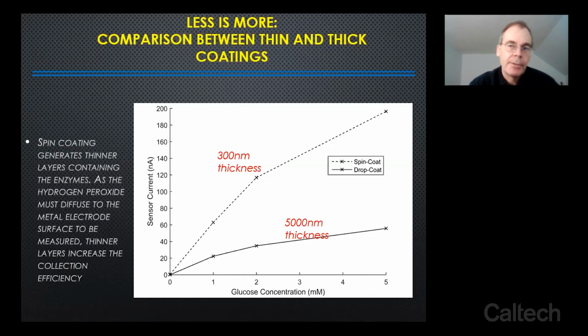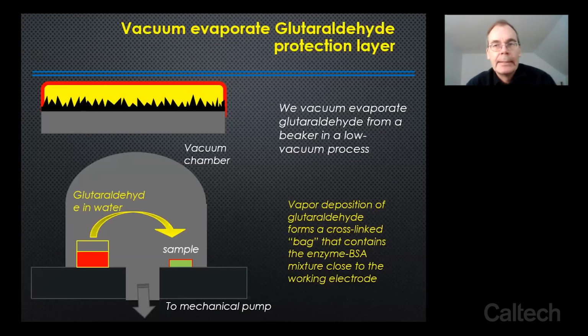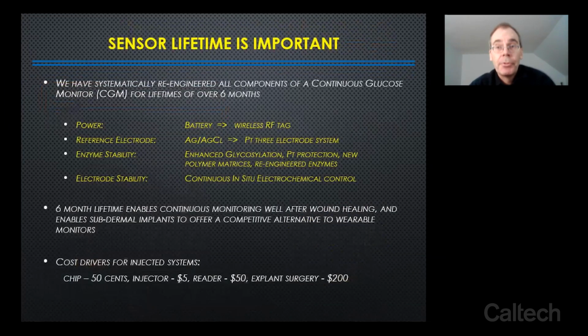It actually makes sense because you generate usually the hydrogen peroxide for our devices with the enzyme reactions on the surface of this thin layer, and then you have to diffuse it through the polymer. So it actually does make sense that thin is good. We also have to do vapor deposition systems. We have to deposit the material that encapsulates this, and we do that by vacuum deposition rather than by painting it on. We also had to change away from a battery. We don't use batteries. We just use these RF tags because the battery itself would be very complex to implant, and it would make the whole device much bigger. So we try to avoid batteries. We just use RF tags.